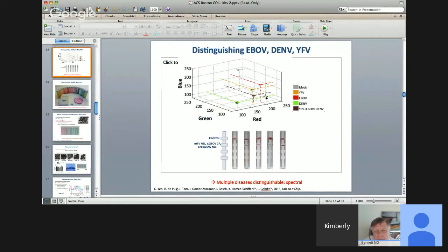If we run, for example, yellow fever through the sample, it has a certain RGB value, which plots here onto this three-dimensional plot. The uncertainty is an ellipse, so the uncertainty in R and G and B is represented by the size of that ellipse. And you can see that for each of the different disease biomarkers, you get different positions on this RGB plot, but they don't overlap. So this indicates that the camera on your mobile phone is able to distinguish between these colors if you break it down into the RGB channels. It's also distinguishable from both the mock and the mixture of all three. So this shows us that we can quantifiably distinguish between different diseases based on the color of the line.